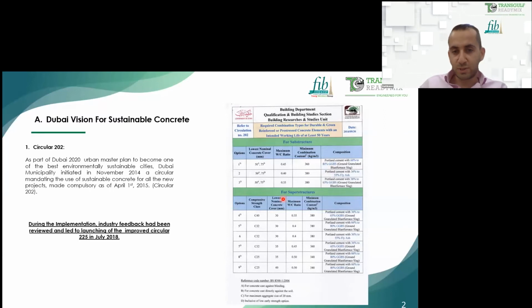Let's go to the superstructure. The superstructure grades are classified starting from 25 MPa, the cylinder strength, up to 40 MPa. Grades beyond 40 and below 25 are not in this circular. Same as the substructure mix, it's classified by maximum water cement ratio, minimum combination, and the composition. All of it has options for the usage of GGBS or fly ash.